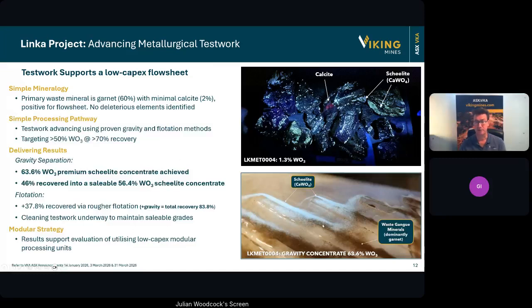The tail from the gravity then moves on to the flotation test work. The flotation step is to recover further material, and our initial rougher flotation step recovered a further 37.8%, giving us a total recovery of scheelite of 83.8%. We do need to continue taking that rougher flotation product and putting it through cleaner flotation stages, and that test work is currently underway at the lab. So we're expecting to be getting results from that in the near future.